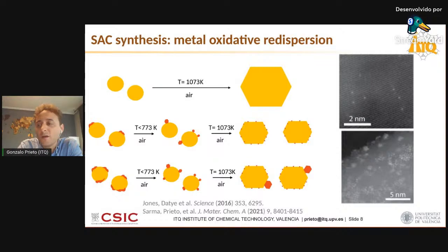But if we move on and we apply treatments at higher temperatures under these oxidative atmospheres, then the metal oxide crystallites become unstable. They disrupt into monoatomic oxo species, which are very mobile at the high temperatures, and they migrate on the surface. They find their way to anchoring sites on the surface of the oxide support. And this leads to isolated metal centers at these anchoring sites. That's the STEM micrograph that I'm showing on the right-hand side at the top.